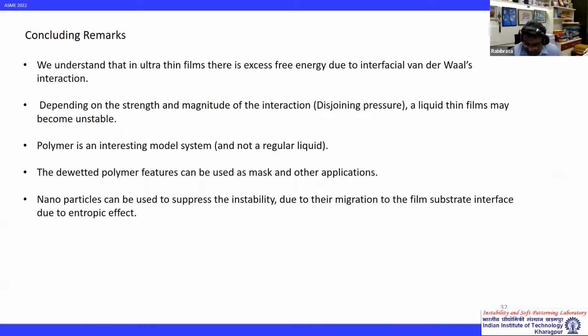So at the end of this pretty disappointing talk, because there are no applications, which is the order of the day, I think we understood what an ultra-thin film is. In an ultra-thin film, there is excess free energy due to interfacial van der Waals interaction. Depending on the strength and magnitude of the interaction, the disjoining pressure, the liquid film may become unstable. Polymer is an interesting model system and not a regular liquid because you have evaporation. Another thing I forgot to tell: if you use a polymer which is solid at room temperature, you can go for higher resolution microscopies like atomic force microscope and scanning electron microscope, which is otherwise not possible with a liquid. The dewetted polymer features can be used for masks and other applications, though dewetting is completely undesired from the standpoint of ultra-thin coatings, and therefore there is a lot of effort on nanoparticle-mediated suppression of this instability.